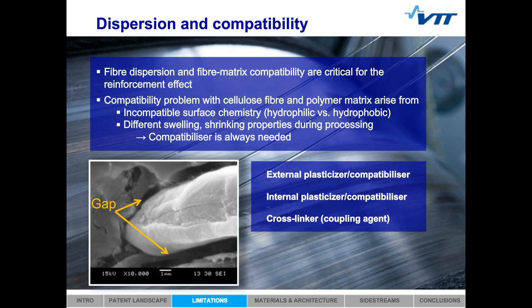And the two main challenges with biopolymer composites are dispersion and compatibility. Most natural fibers tend to be hydrophilic, whereas most of the matrices are hydrophobic. And for this reason, a compatibilizer is almost always required to get the best performance. And for the same reasons, achieving effective dispersion is equally challenging. And we often need to employ a good method to disperse the fiber inside of the matrix.